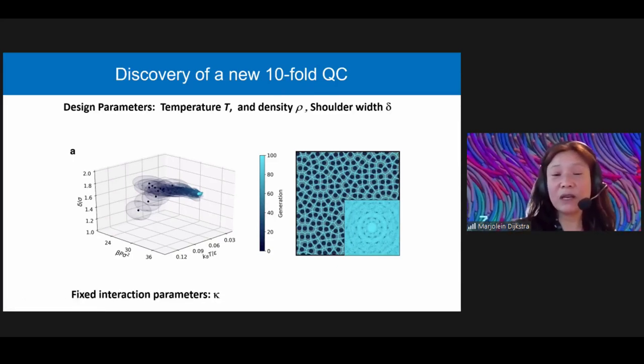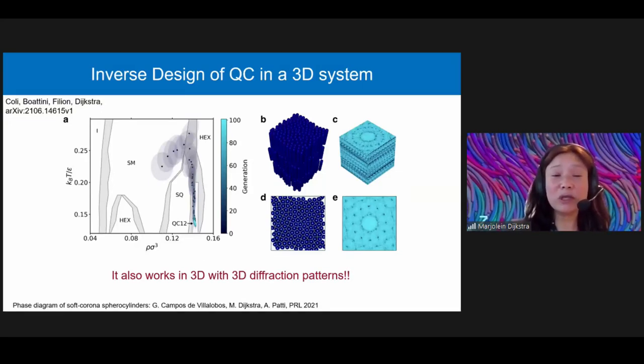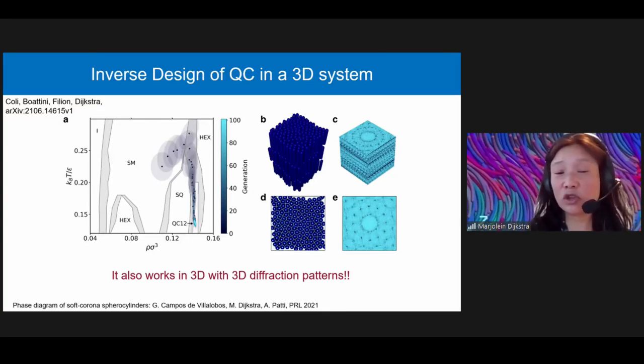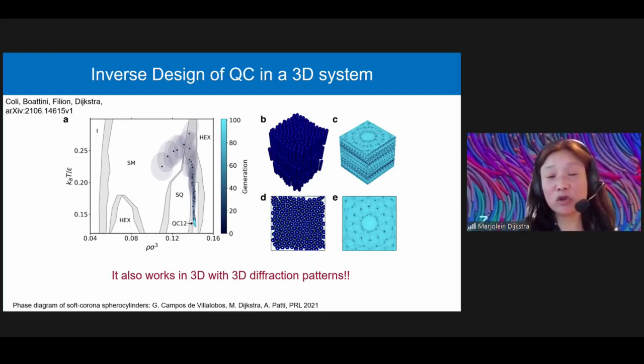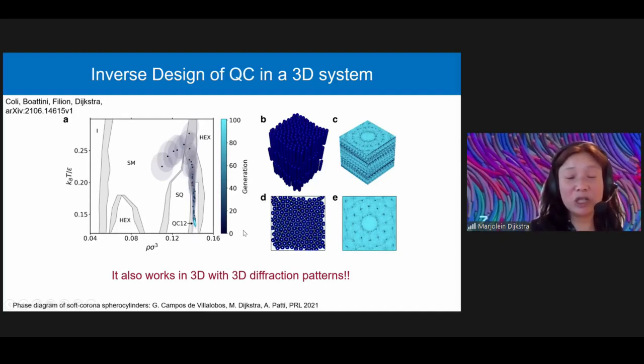phases, and in this case we were also able to discover a completely new quasicrystal phase, which is the 10-fold quasicrystal phase. Finally, we extended it to a 3-dimensional system, colloidal rods coated with, for instance, a microgel, which have a soft shoulder as well. These systems can also form smectic layers with quasicrystalline order, and also in this case, by feeding in just 3-dimensional diffraction patterns, which are difficult to interpret by the human eye, the neural network really doesn't have any problems with increasing the dimension of these diffraction patterns, and was able to also find this quasicrystal in this system.